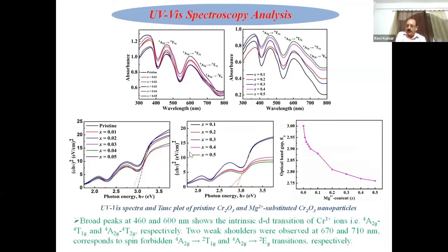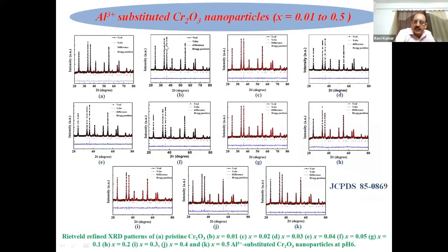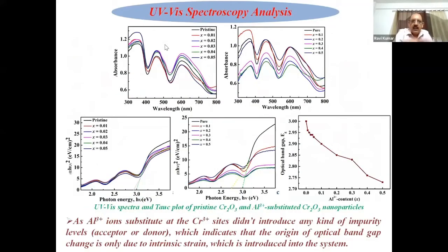Then UV visible spectroscopy. Now, UV visible spectroscopy, again, I am telling you, the chemistry people are somehow doing better analysis than physics people, because physics people are only bothering about the Tauc plot, band to band transition. But I will tell you the electronic structure of the electronic transition, because when you have an octahedral symmetry and there is a crystal field splitting taking place of the d orbitals, and that transition is also lying in a UV visible electronic transition. So here you see there are different kinds of electronic transitions there.